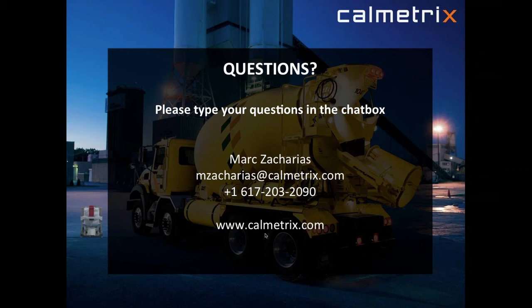But in terms of doing continuous mixing, no, you can't, because if you do continuous mixing and continuous measurements and want viscosity continuously, it won't work, because here you have your trade-off, your dilemma. If you use traditional impeller shapes, you can use the Bingham equation, but you don't mix well, so the concrete will segregate. So whatever values you get are junk, right? But if you have a Rushton impeller, there's no mathematical model, unless someone wants to start working on it. There is not, as of today, a mathematical model that correlates the two.